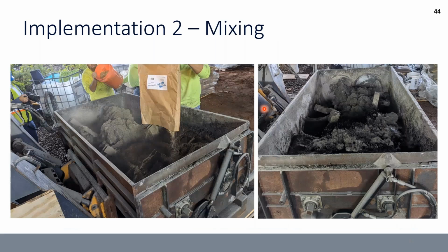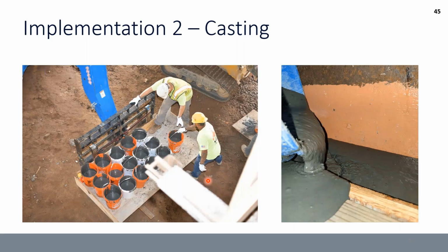For mixing, every material supplier, when we're using commercial mixes, has different methods that are preferred. So this is the one that was used by Cortoff, and it's mounted to a skid steer. Casting, we were able to just have a lot of those 5-gallon pails, lift them up with a boom lift, and fill from the top. And then the contractor did choose to go back and grind the surface to get the grade that was required, rather than doing any top forms.